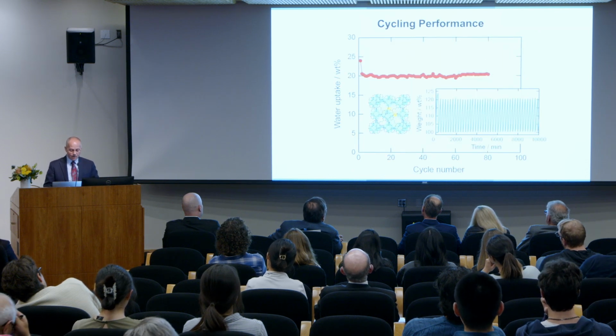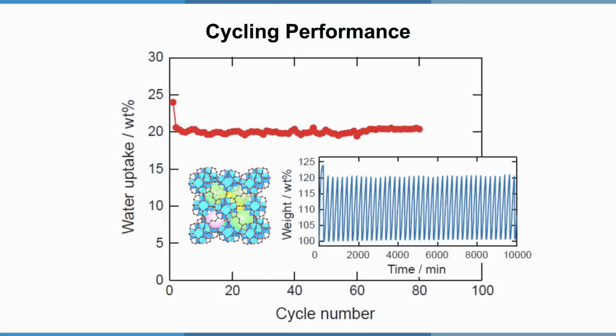And the nice thing was that this material cycles back and forth. You can take water in, water out. It doesn't decompose. Nothing happens to the material. But what we noticed is after the first cycle, there's a drop in capacity. That means that some of the water was staying in the pores. It wasn't coming out.